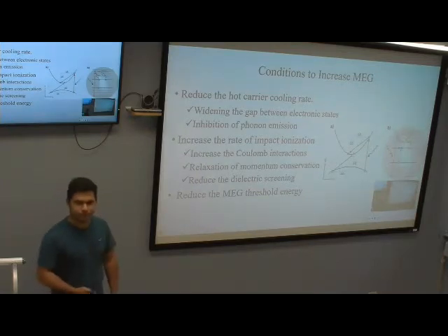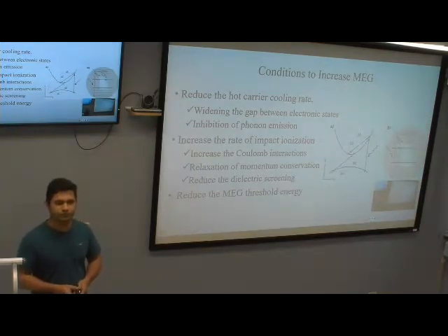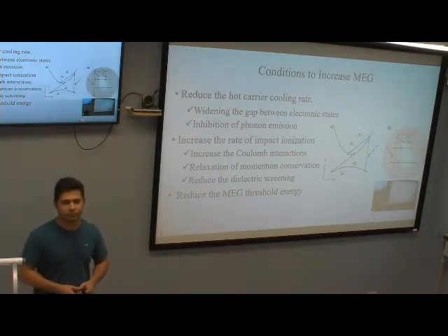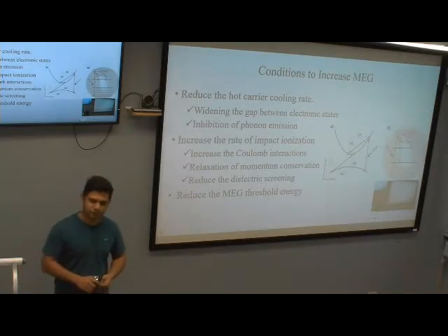Back to your question, in a nanowire you have one dimension which has to be periodically extended, right? So you are reducing the requirements for momentum conservation. Now you conserve momentum only in this direction. The other two, you don't need to worry about, right?